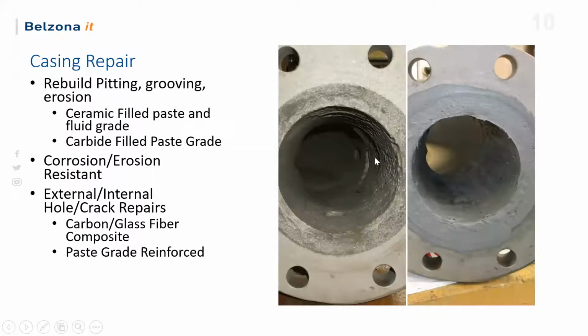This is another one that had a through wall hole right here at the pump outlet on the casing. So they filled it in with our paste grade material. The hole was filled in. We also put some composite reinforcement sheets over the hole, kind of like rebar and concrete. So we have reinforcement sheets that we put over holes, build it up, smooth it out, and then two coats of epoxy. So it can be used to fix scenarios where you think it's beyond being fixed, we can go in there and fix it correctly.